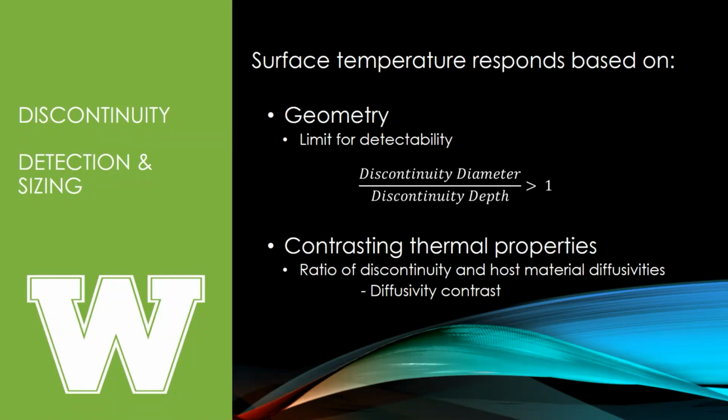It's not great at finding the narrow cracks like you would find with eddy current testing. It's not great at finding the narrow cracks you would find with dye penetrant or with mag particle. But what it is good at finding is things that tend to be wider area: impact damage in a composite surface, crushing of the honeycomb in a metal surface, if you have a metal honeycomb, or water that's made its way inside of an object that kind of spreads out, that diffuses out. That's what you're going to find.